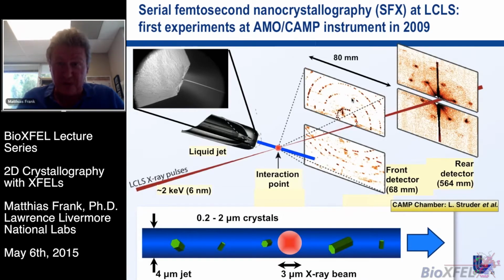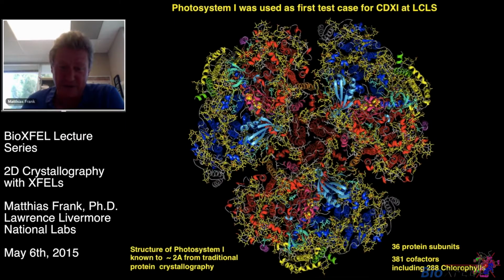So this picture is actually from one of the first experiments in femtosecond nanocrystallography at LCLS. This is a picture from a very first experiment at AMO where the detector was not the CSPAD but a different kind of CCD detector. A liquid jet was used to shoot a jet of microcrystals of photosystem 1 across the interaction point with the X-rays. The X-ray pulses were interacting with crystals, and down here is schematically shown a 4 micrometer diameter water jet with some small crystals in it. The X-ray beam diameter in this experiment was about 3 micrometers. And occasionally a crystal is going to be in the right place at the right time, and you'll get a diffraction pattern.